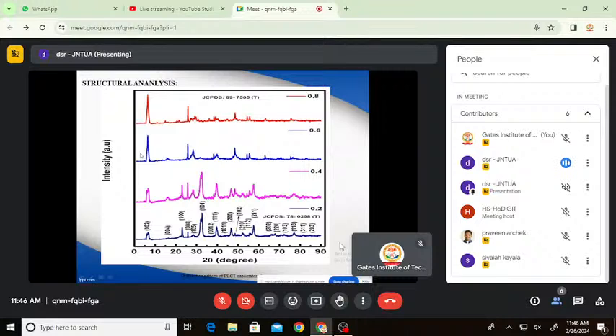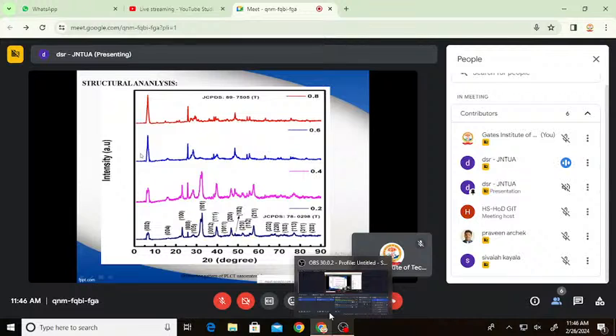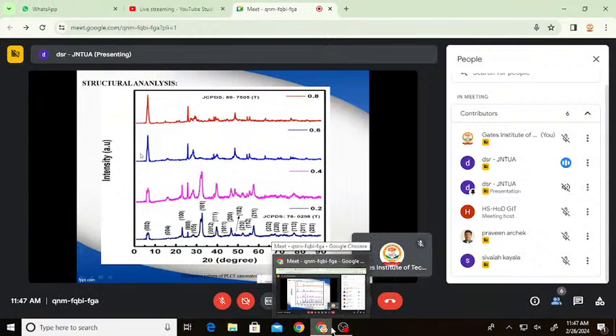It may be achieved because of the existence of enriched lanthanum content. Therefore, Z equal to 0.6 and 0.8 contents, they ascribed the tetragonal structure of PLCT matches with the JCPDS files having the number. Finally, from the investigation of this PLCT nanoparticles XRD patterns, it is known that larger concentrations dominate the structure formation.